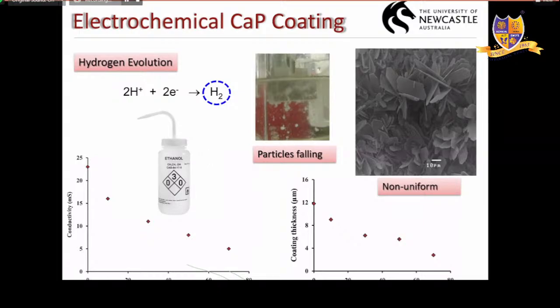So what we did for the first time was to control the coating kinetics. We thought, let's increase the resistance, in other words, decrease the conductivity of the electrolyte. So we used a solvent, ethanol, at different volume percent, and measured the conductivity. As expected, the conductivity decreases with the increase in the ethanol content. And we did some coating. As you can see here, the coating thickness has decreased with the increase in the ethanol content, which is expected.